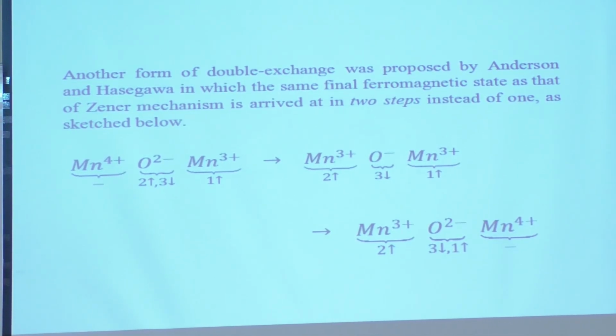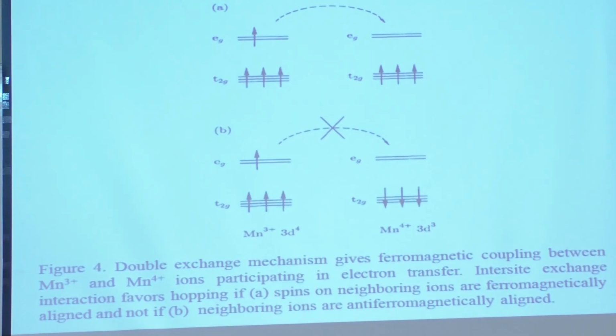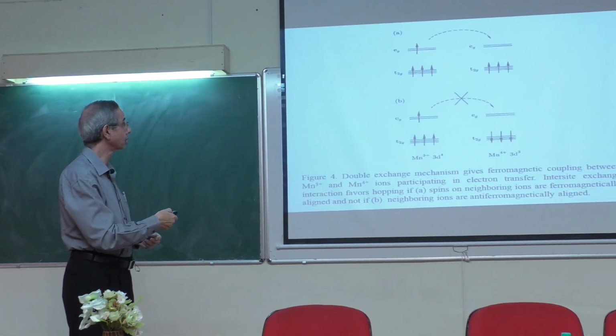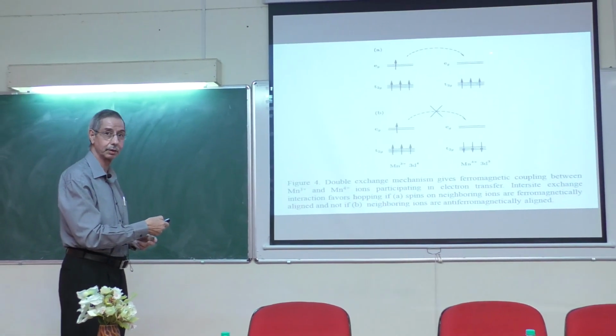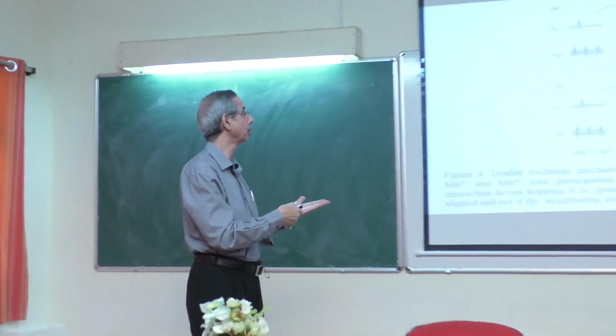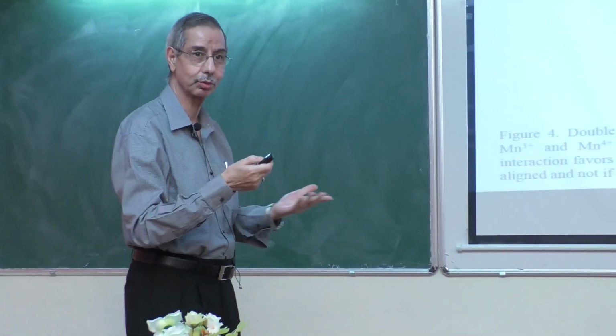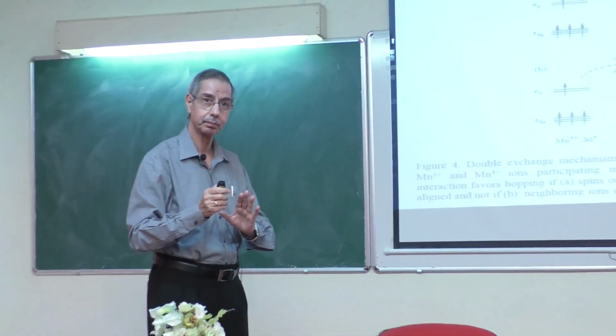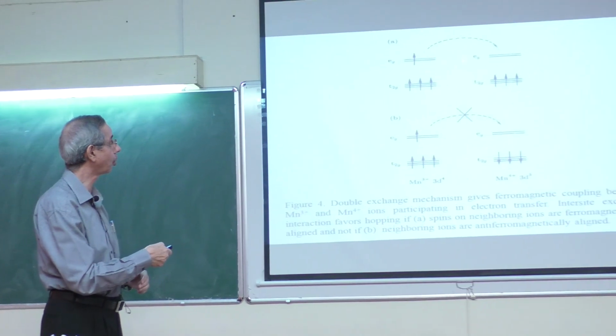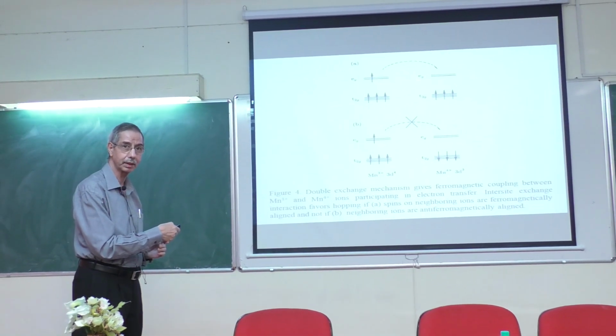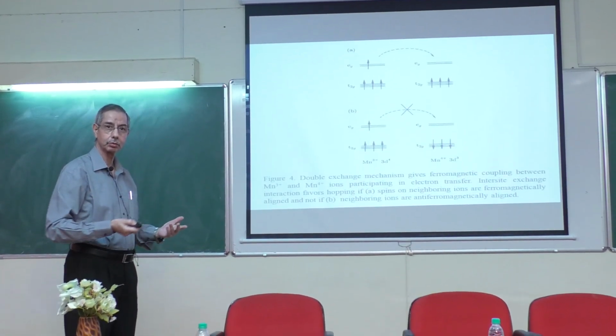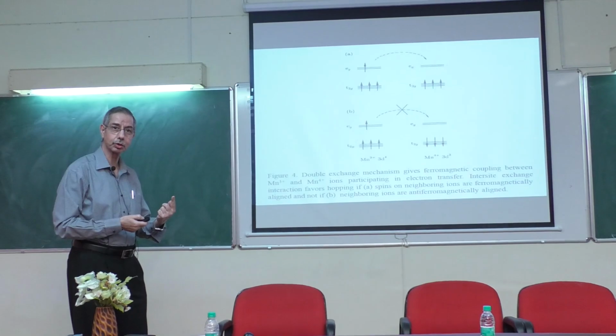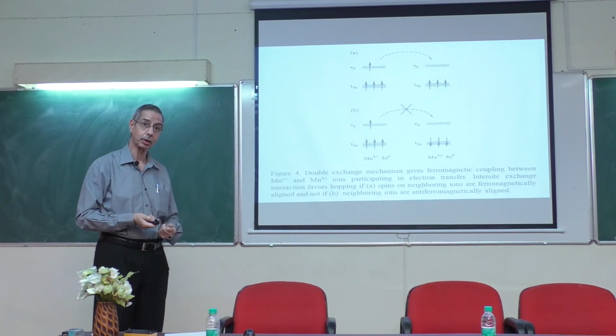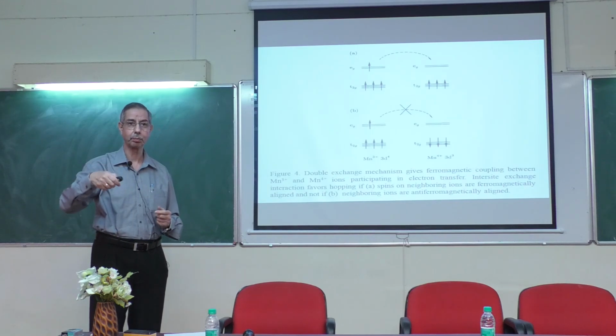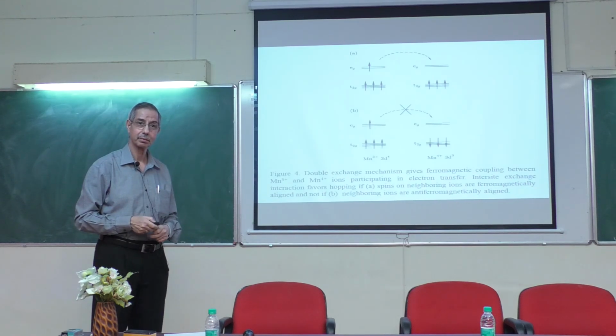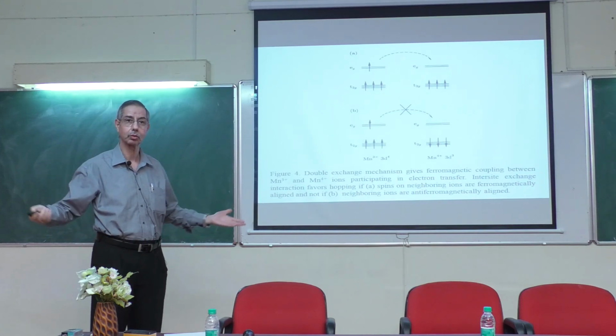Super exchange doesn't operate because of the fact that, you remember what the problem with super exchange was? We had the same valence states on this side and that side. That means I was dealing with either manganese 3 plus or manganese 4 plus. If you had systems with the same valence state, then hopping to the O2 minus side is most improbable, because there you have to pay both the Coulomb cost plus the exclusion principle. That is, you have to pay both costs. So that is highly improbable. So if this does not hop, then that is why they are insulators. There is no possibility of conduction to take place. There is no conduction electron.